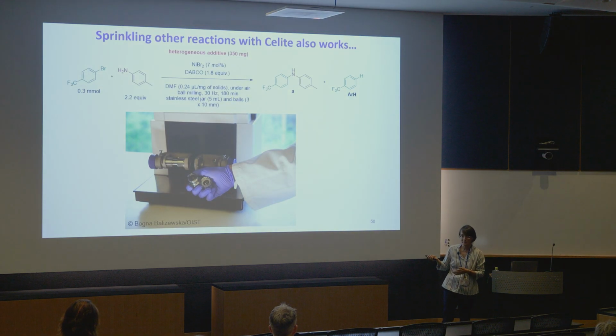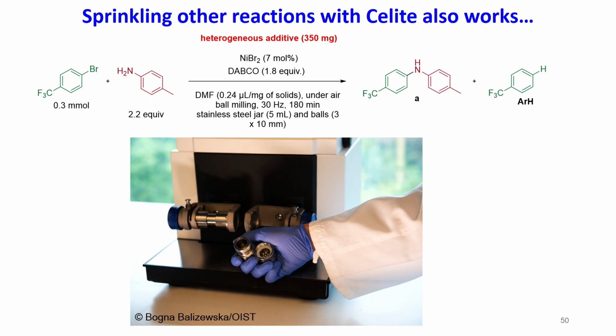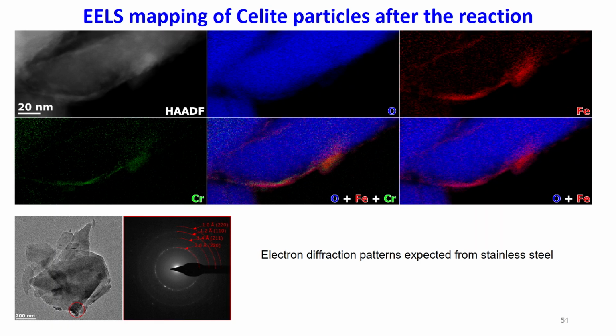So the setup that we use to run the reaction is this. We have a jar and balls, and they may be made of different materials. Would it be tungsten carbide, zirconia, or stainless steel? Stainless steel is the cheapest one. That's what we use most of the time. And that's exactly where iron and chromium tend to be co-localized. And we actually confirmed that, because if we check the electron diffraction pattern of this little coating on the Celite particle, we see the pattern that we expect from martensitic steel that is used in these jars and balls.